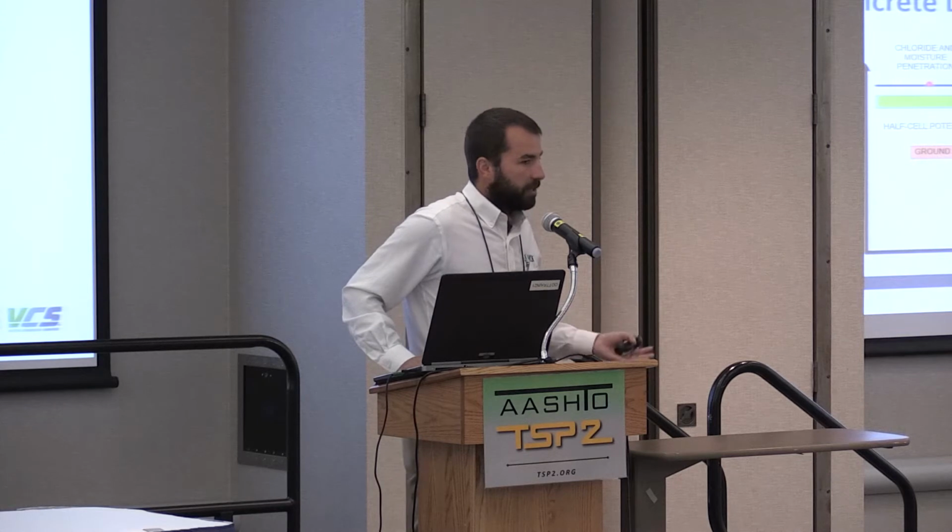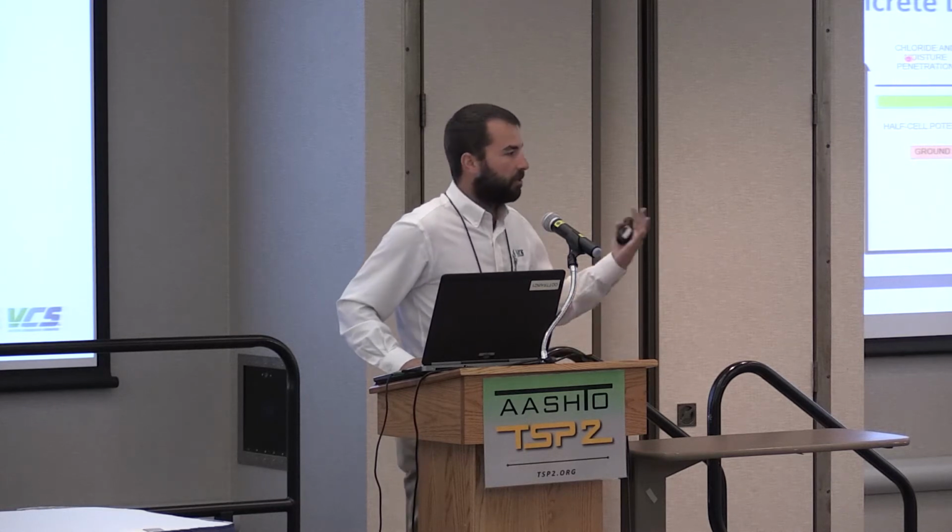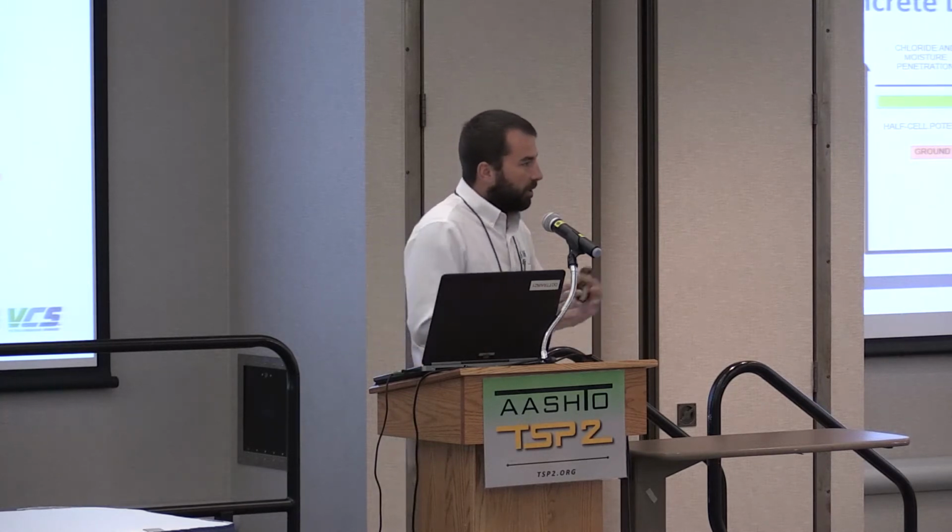Techniques like electrical resistivity can identify if the concrete resistance is being lowered by chlorides and moisture. Corrosion potential, half-cell, identifies active corrosion. GPR can identify a wide swath of things, so maybe we could use GPR. Impact echo is better at identifying delaminations earlier in that phase, and I'll talk a little bit about these.